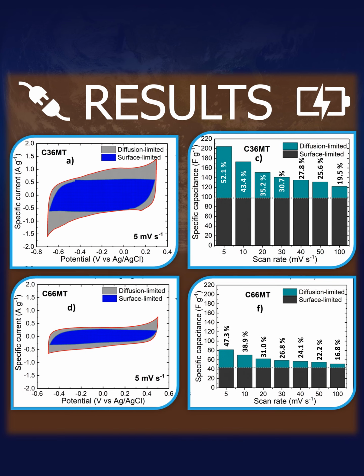On the other hand, we see how the electrochemical results change when the material receives an oxidative calcination at 300 Celsius degrees and when it doesn't receive it. So when the material receives an oxidative calcination, it increases the electrochemical properties, as we can see in the figure A. And in this case, thanks to the increase in the surface area, we also see an increase in the capacitance delimited by the surfaces, as well as diffusion limit, because functional groups also increase.